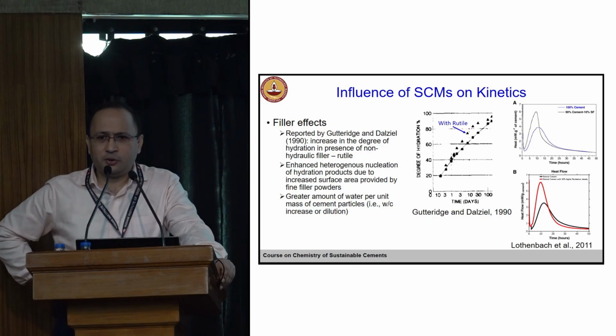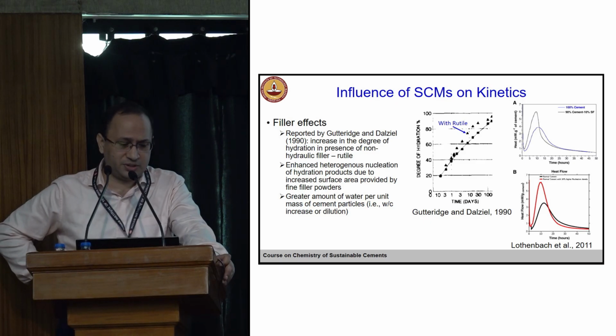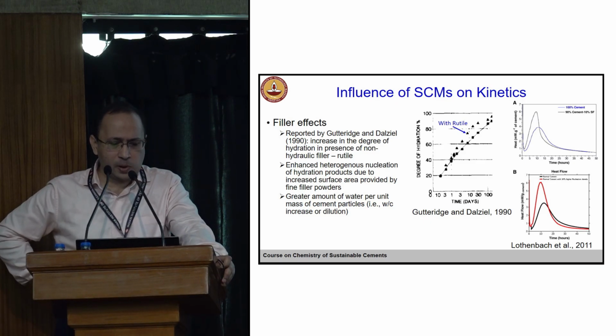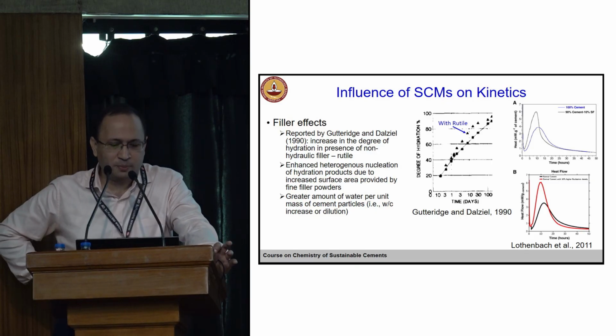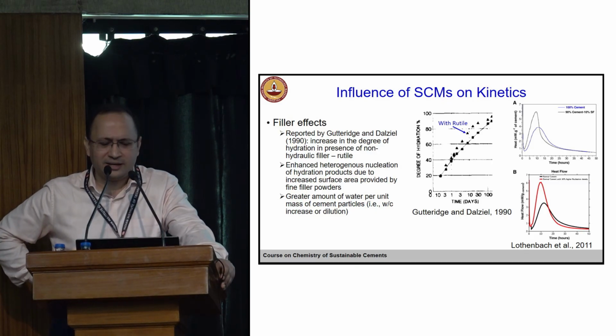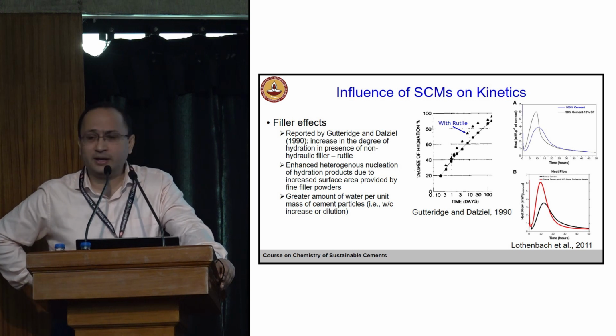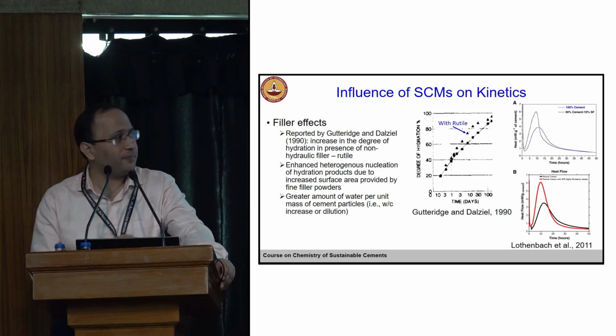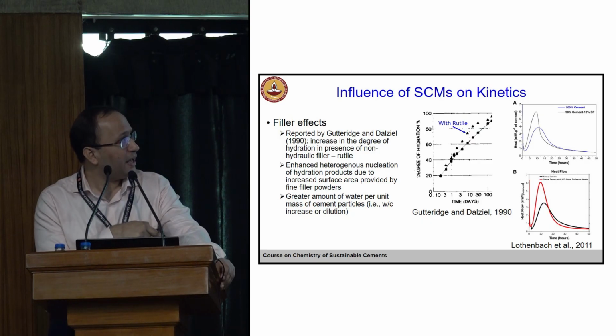So what could be the reason for this? There are a lot of effects which take place. A lot of changes are there, all right? You provide increased surface area, you have more water, more water per unit mass of cement particle when you use these fillers. So overall, these things result in improvement in the heat of hydration. And you can see a similar effect here also when silica fume is added to PC, how it increases the heat of hydration.